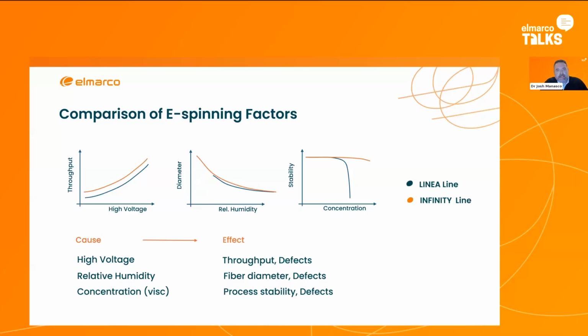So what we really see with this process is that one of the main ways to control throughput is voltage. So the higher the voltage, the higher the throughput, but then also the more defects because you're causing a more chaotic process. And what we see is that this extra stability of not stopping and starting those spinning jets all the time gives us the ability to turn that voltage up a little higher, or to maintain the voltage but see fewer defects being produced. But also we see a little bit more throughput because we're not interrupting, again, stopping and starting the process all the time.